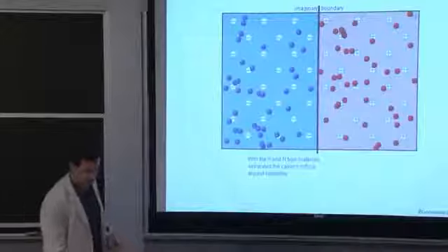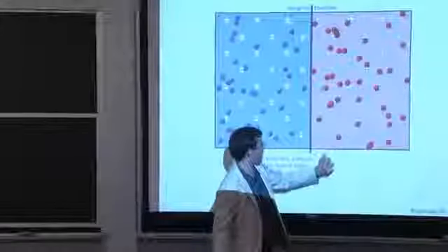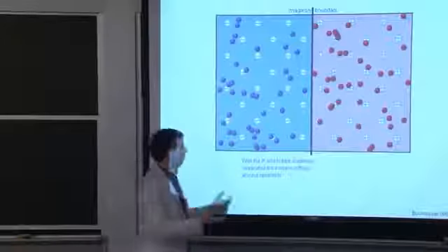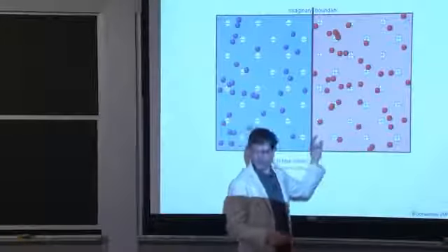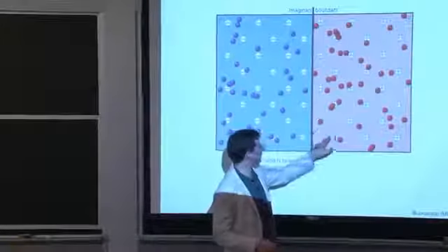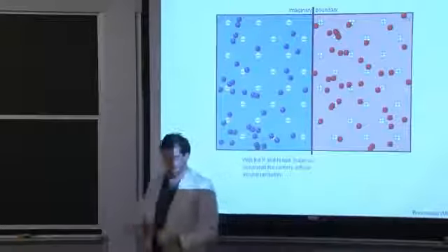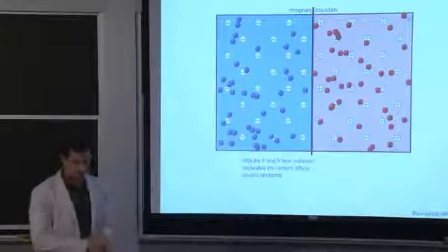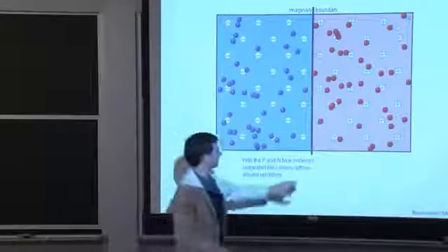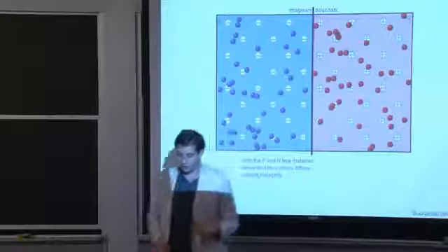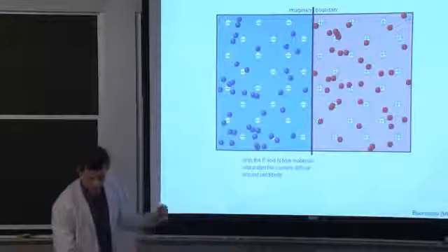They're in the conduction band. They're able to move. And because the binding energy to the phosphorus atoms is on the order of 10 meV, the thermal energy here at room temperature is enough to dissociate them and to allow those electrons to move away from the phosphorus atom, thanks to the screening potential of the surrounding lattice and thanks to the fact that electrons inside of a crystal can more easily move than in vacuum.